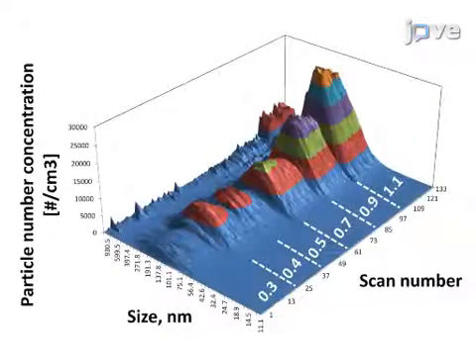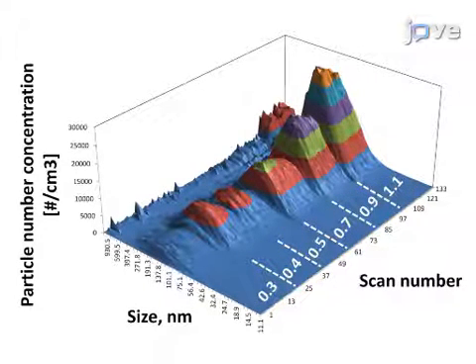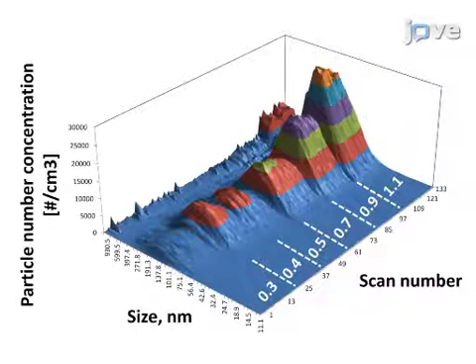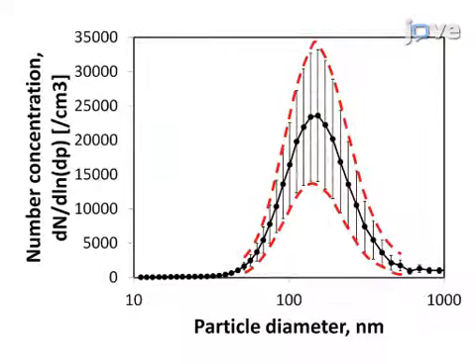Here, the particle size distributions from aerosolization flow rates in the range of 0.3 to 1.1 liters per minute are compared to learn their effects on aerosol generation. The peak of the spectrum rises as the flow is increased. At the highest flow rate, a secondary peak appears, indicating micron-size airborne particles. Particle size distributions vary to some extent within each test and between tests done with the same powder. The variation from four replicate tests of the same material using identical flow rates shows a standard deviation of about 40% for total particle concentration and 7% for geometric mean size.